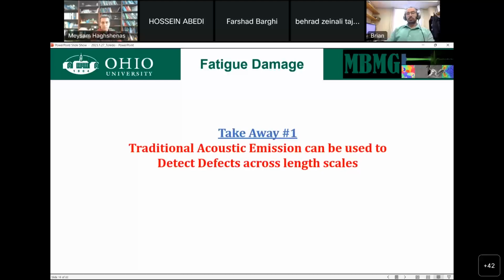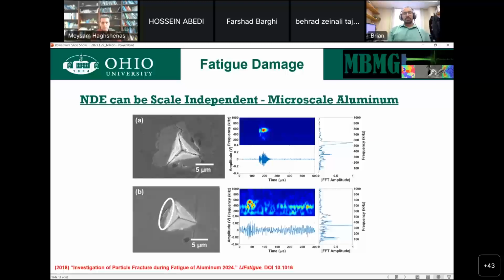So the same sensors that we use if we're trying to find macro cracks, large scale defects, we can use those same sensors to try to find small scale defects as well. The trick is knowing what the level of noise you have is and what the defect sounds like to be able to identify it. For example, this is a study that was done back in 2018, right before I left Drexel, we've done this here since, but this is still some of the best results I've obtained, where if we look at this image, there is a difference in grayscale.